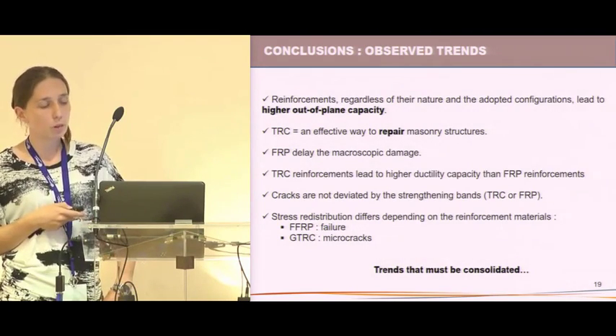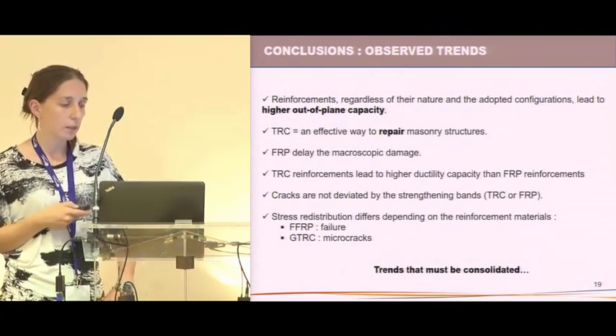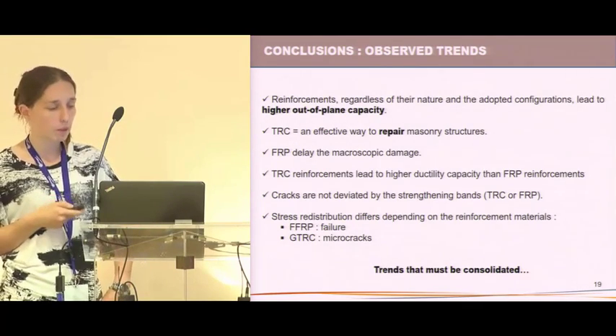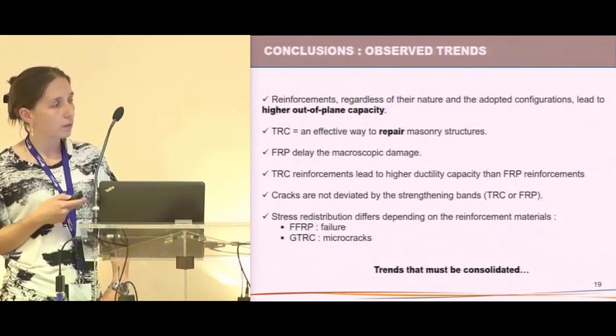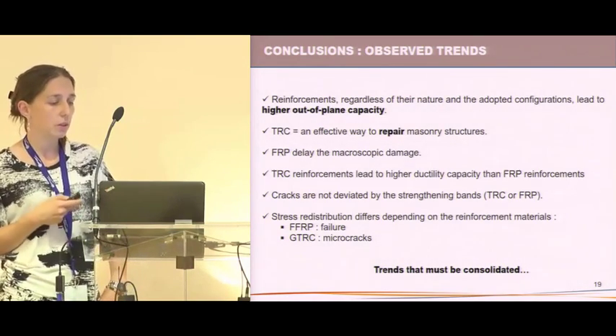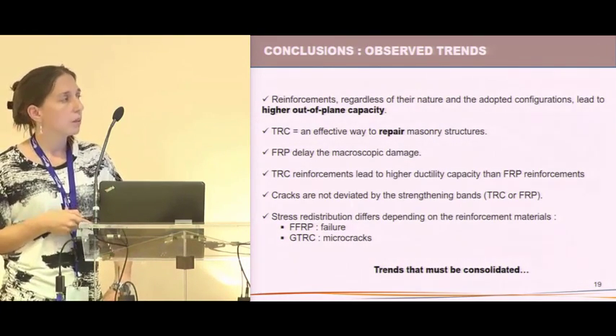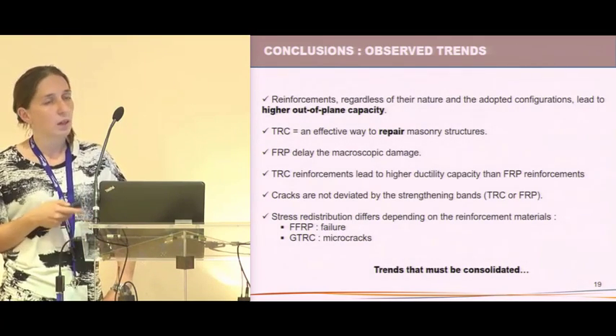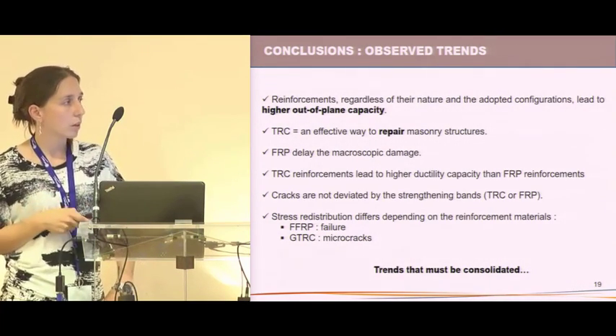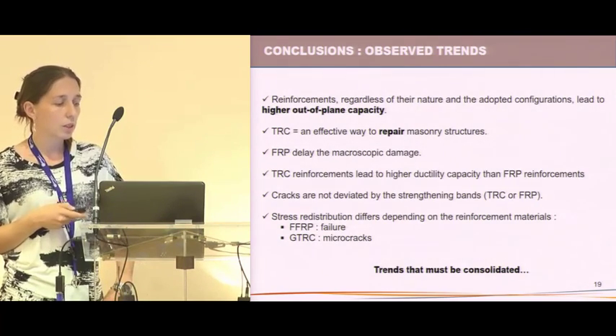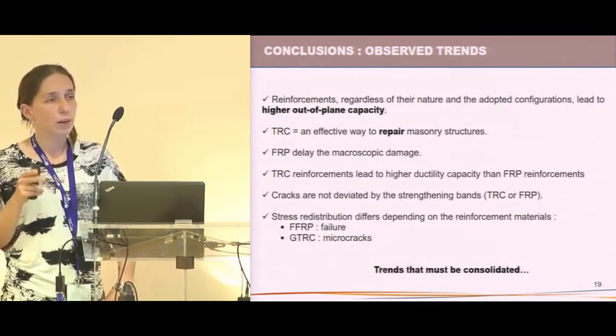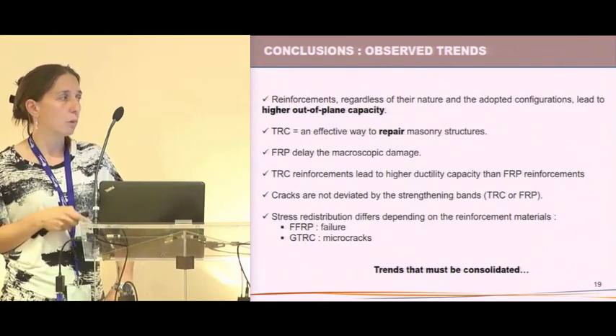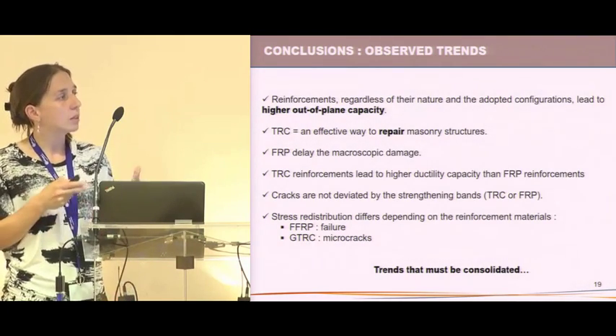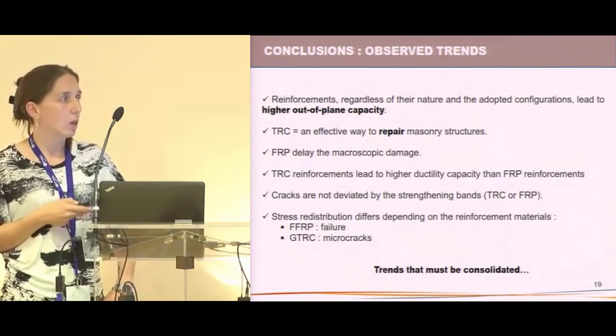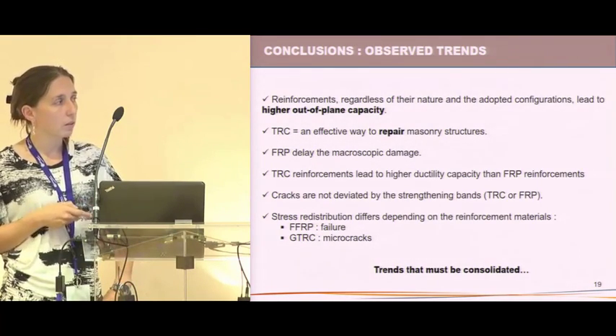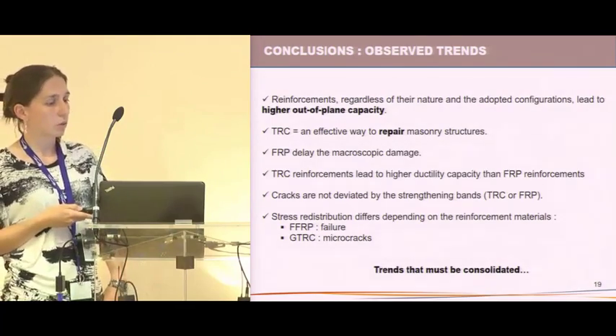About the failure mode, we can remind that cracks are not deviated by the strengthening bands, and it appears that stress redistributions differ depending on the reinforcement materials: in the case of flax FRP, we have a failure on the central horizontal band, but in the case of GTRC, we have only microcracks on the outer face of the bands. So we have an interaction between the substrate and the materials which is different depending on the case. Thank you very much.